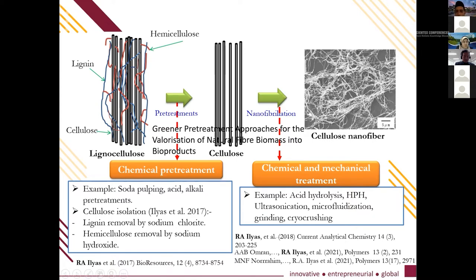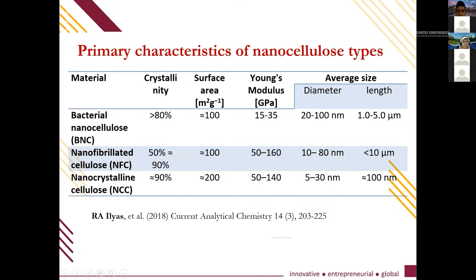You can refer to my several published papers. Regarding the primary characteristics: nanocellulose can be divided into three types — bacterial nanocellulose, nanofibrillated cellulose, and nanocrystalline cellulose. From plants, we get nanofibrillated cellulose and nanocrystalline cellulose, while bacterial nanocellulose comes from bacteria or algae. The highest crystallinity belongs to nanocrystalline cellulose, which also has the highest surface area, though it depends on the intended application.